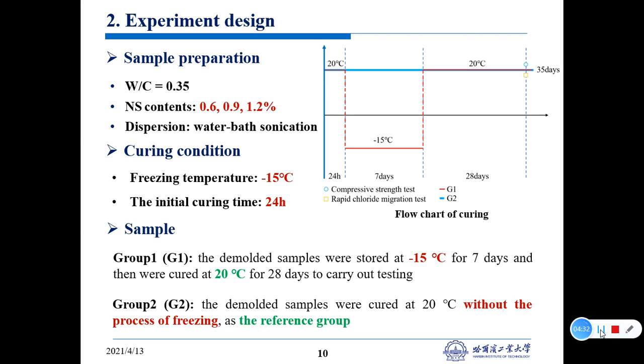And for the curing condition, the freezing temperature is minus 15 degree, and the initial curing time is 24 hours before demolding. And the samples are divided into 2 groups. We can see this flow chart of curing like this. The group 1 samples were stored at minus 15 degree for 7 days, and then were cured at 20 degree for 28 days to carry out the testing.